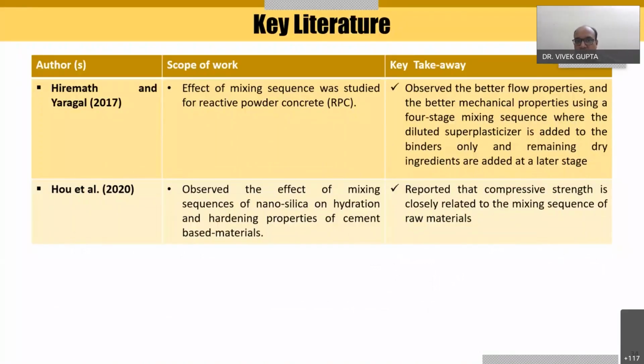So these are the different literature. For bricks, we don't have much literature, so I put in some literature where Hiremath and Yaragal in 2017 observed the effect of mixing sequence on reactive powder concrete. They observed better flow properties and better mechanical properties using a four-stage mixing sequence, where the diluted superplasticizer is added to the binders only, and the remaining dry ingredients are added at a later stage.